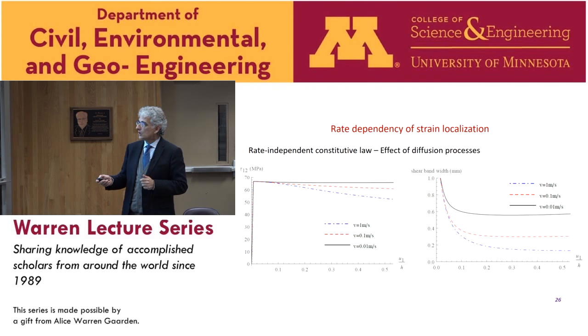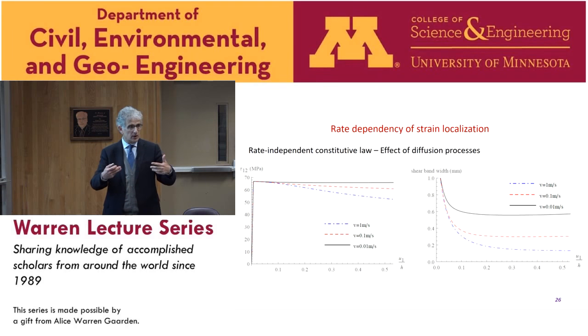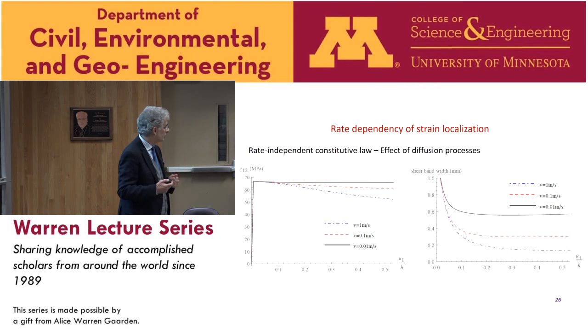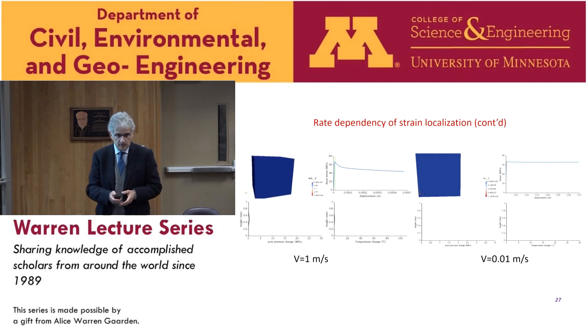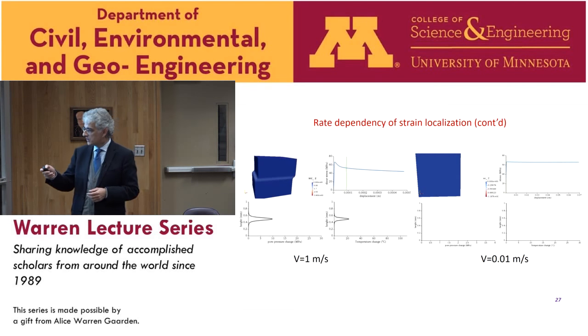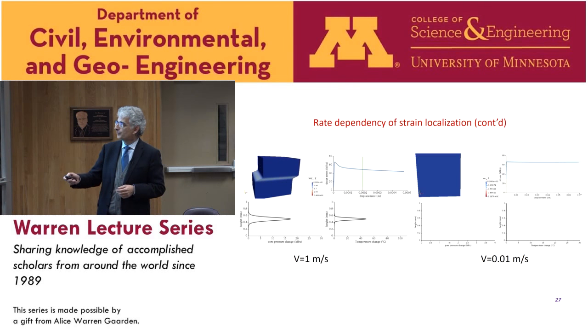So if we consider a slip rate which is not too high, then the thermal pressurization effect is not strong enough to induce real softening. But the softening is more noticeable for faster shear rate. And this is linked, you see, to the shear band width, which becomes smaller and smaller for faster rates. And yes, this is illustrated here. So this is the same simulation as before with a velocity of 1 meter per second.